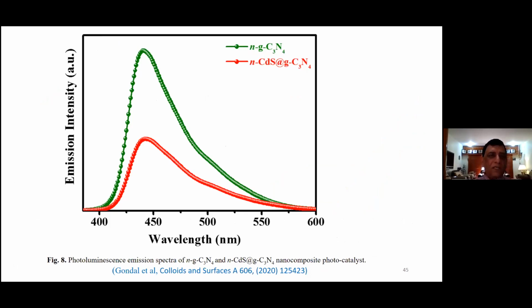This is a photoluminescence spectrum, again you can see we can control electron hole recombination. Pure graphitic carbon nitride you can see is green, while when we have this nano composite, the emission has decreased almost more than 60%. So electron hole recombination is controlled very well by this nano composite.